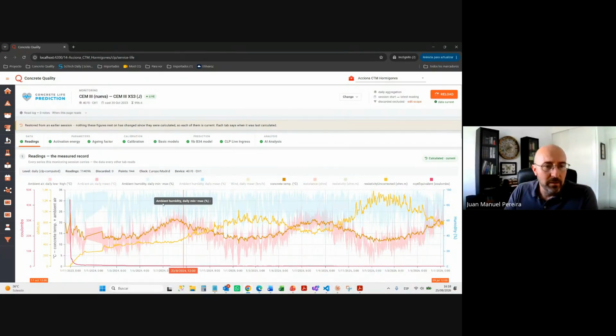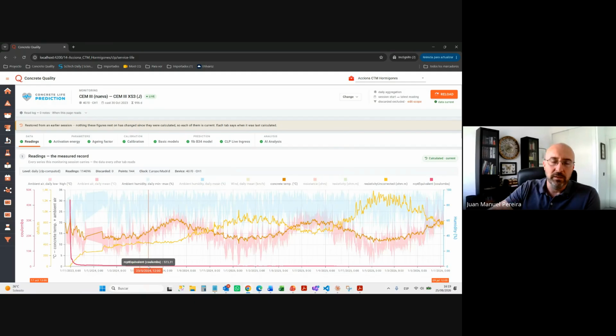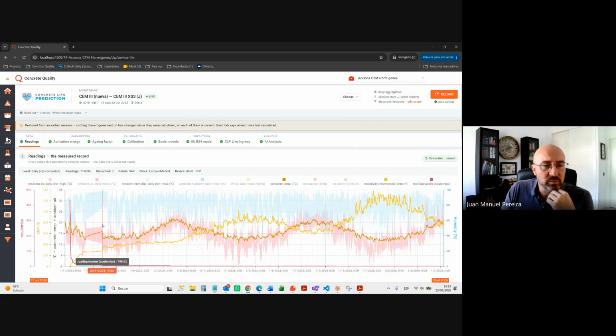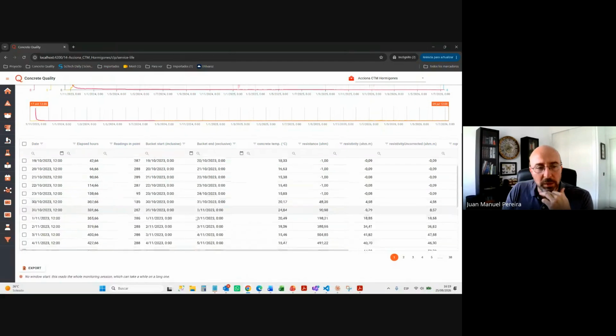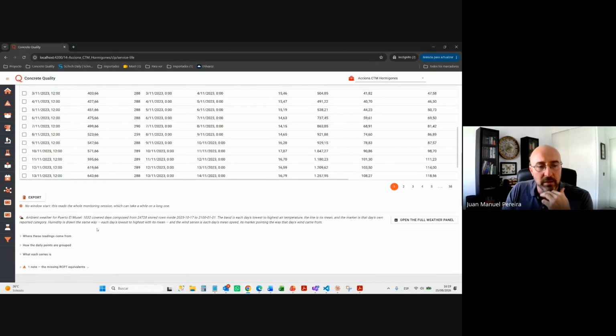We can also derive RCPT directly, because there's a direct correlation between electrical resistivity and the rapid chloride permeability, because it's an electrical test where you measure the charge transmitted through the concrete. So the electrical resistivity is part of that. It's basically applying Ohm's law kind of directly. And of course the software allows you to see all the readings and export the data, etc.